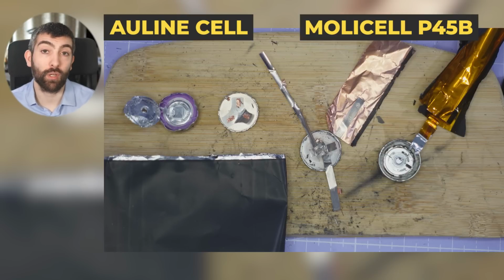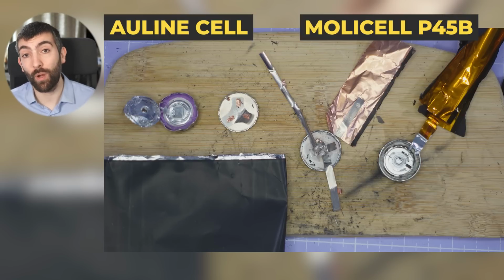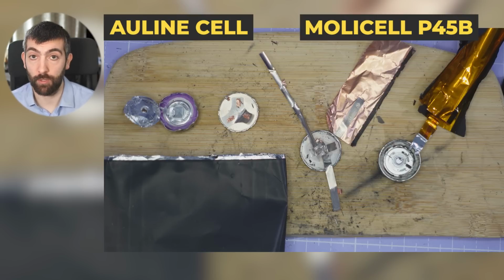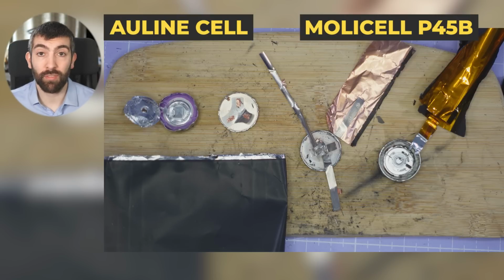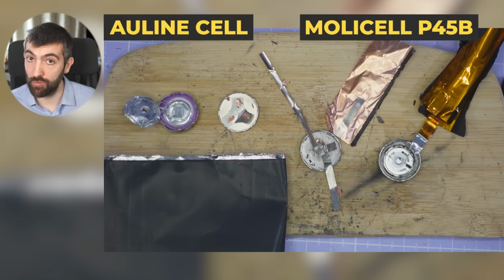Compare that to the Molicell P45B. We have no exposed strip of foil. Instead, we have several thick tabs that extend deep into the battery and are spot welded to the foil. These tabs are then welded directly to the positive and negative terminal of the battery with no interposer. It's my belief that this is a lower resistance way to construct a battery. The addition of that interposing piece, that interposer is going to introduce extra spot welds, which will introduce extra resistance.